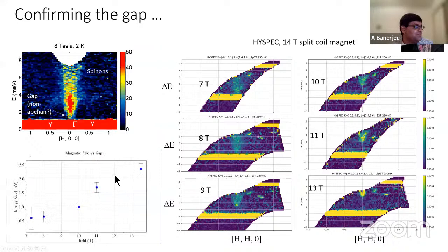And not only that, what we would be able to show is that there is indeed an energy gap beyond the error bars at all points of time, roughly half a meV, so 5 Kelvin gap. So 5 Kelvin is a big gap, actually, I would have to say. So anyway, so that's where everything is right now.